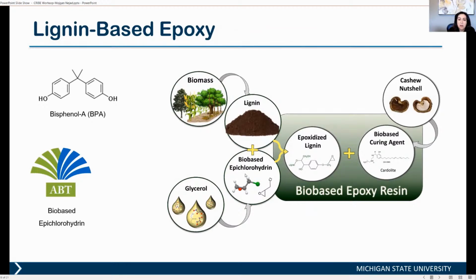This bio-based epichlorohydrin is actually produced from glycerol, and lignin, as you know, is produced from biomass. We mix them together to make epoxidized lignin, and in epoxy resin, we need a curing agent to cure it. For that, we also use a bio-based curing agent, cardolite, and there are different cardolite bio-based curing agents. In this case, this one is produced from cashew nut shell.